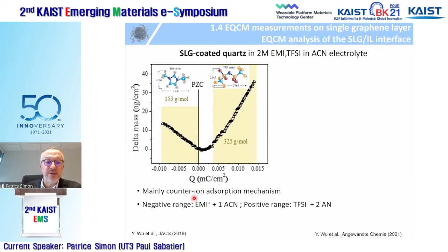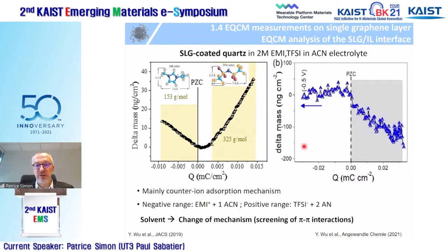And you can see that both of these ions are partially desolvated, because one cation adsorbs with only one single solvent molecule. One anion adsorbs with two acetonitrile molecules. This can be easily calculated from the molar weight of the anion and the experimental molar weight here. So this is a partial desolvation. And if you compare what you obtain between EMI-TFSI in acetonitrile here and single layer graphene in neat EMI-TFSI, you can see that the presence of solvent changes a lot the charge storage mechanism, just because you screen the pi-pi interactions which exist between the sp2 carbon of the graphene and the EMI plus cation.